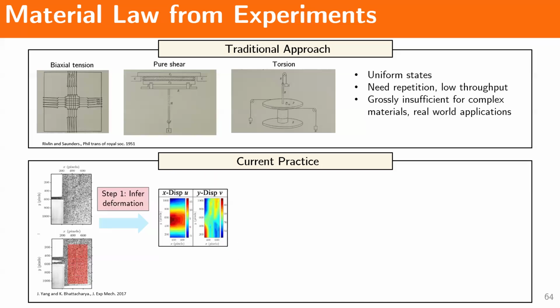So non-uniform strain here, for example, if you have cracks or holes, you have complex states in the material that can give you more information to then be able to back out a model from these non-uniform strains, right? Because you're sampling basically multiple different strain states in the material at once within a single experiment. So that gives you more data for your model. But of course, there's no free lunch. Now you have to solve a more complex inverse problem.